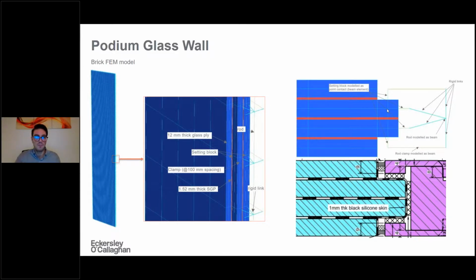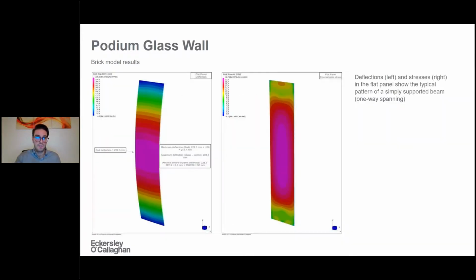And so we had to build also this model. We tried to be very accurate in building this, and we did it for both flat and curved panels. And what we saw from here, which was also something shown by the global analysis, was that clearly the flat panels are very much simply supported, behaving like a simply supported beam spanning between the two rods, with then a bit of lower stress here, where the glass is also supported by the top and bottom shoe to the steel beam.